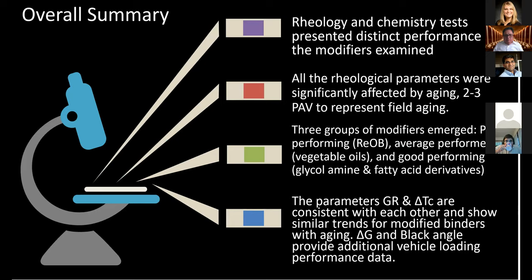So quick summary of the project: rheological and chemical tests presented distinct performances of all the modifiers, which is what we were looking for in this study. All the rheological parameters were significantly affected by aging. 2 and 3 PAV seem to represent the best field aging. 3 groups of modifiers emerged. You saw the poor performing REOB, average performers the vegetable oils, and the good performing were the glycolamine and fatty acid derivatives. The parameters of Glover-Rowe and Delta Tc are consistent with each other and show similar trends for modified binders with aging for those low temperature criteria. Delta G and the black angle provide additional vehicle loading performance data at the intermediate temperatures.